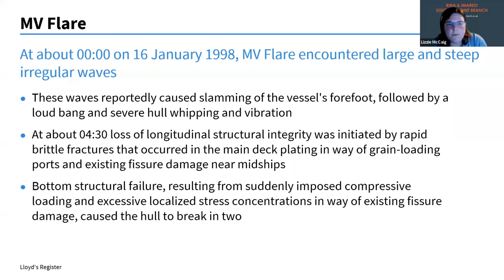And then at 4:30, there was loss of longitudinal structural integrity initiated by the rapid brittle fractures that had appeared in way of the existing damage near midships. There was then bottom structural failure, which resulted from suddenly imposed compressive loading and localized stress concentrations, which then caused the hull to break in two.